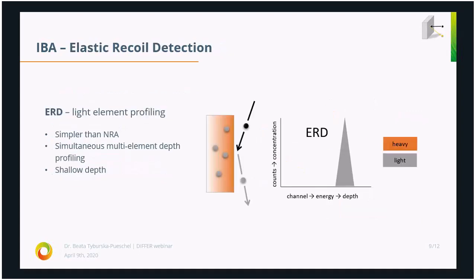Then we have another technique which is called elastic recoil detection, and that one is used for light element profiling, mainly for profiling of hydrogen and deuterium. And so again, we have a heavy matrix and light particles in it. And then we have an incoming beam, but this time it's not perpendicular to the surface anymore, it comes under a grazing angle. And what it does is simply kick off hydrogen atoms from the sample, and those recoil atoms are being detected.